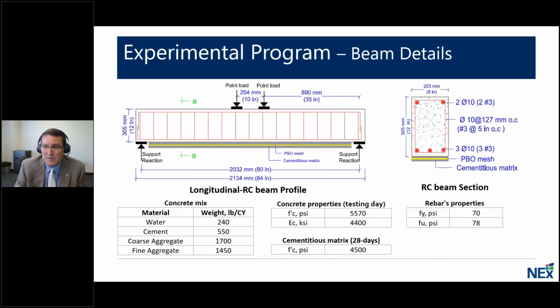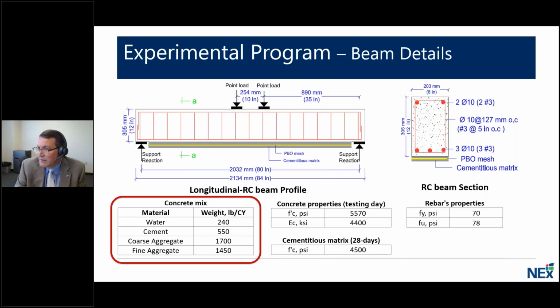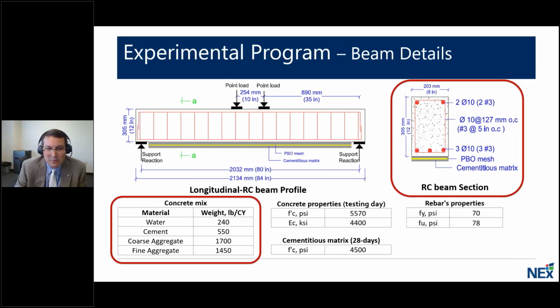Here are the details of the reinforced concrete member, including the mix design, the FRCM matrix, and the rebar as shown. For these repair studies, what we try to do is utilize mix designs that are vintage of the type of concrete we would be trying to repair in the field, both in terms of what's used in the mix design. So we wouldn't necessarily be using today's admixtures. And also we would be trying to develop properties, including the compressive strength, that are representative of field repaired structures. You can see the details on the beam here and the reinforcement that was used. Again, the reinforcement level would be representative of what we would expect to see in an element in the field.